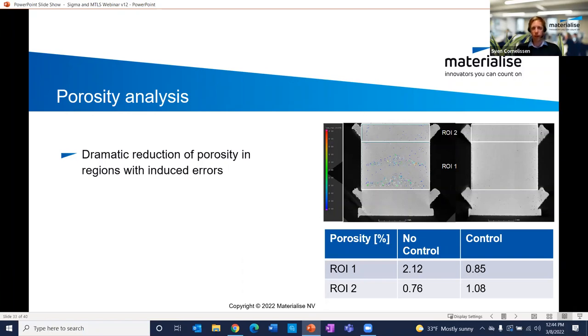And so if you look at region one, where on the left you have the reference experiment with obviously all the errors inside, you can see that if you look at the same zone in the experiment with closed loop control, the porosity is dramatically decreased, right? So it's improved. We're taking out all of the pores. If you look at another zone, for example, this zone on top, which we called region of interest two, which is a zone in principle without induced errors, so running at nominal values, then you see that the porosity is slightly increased. Come back to that later.